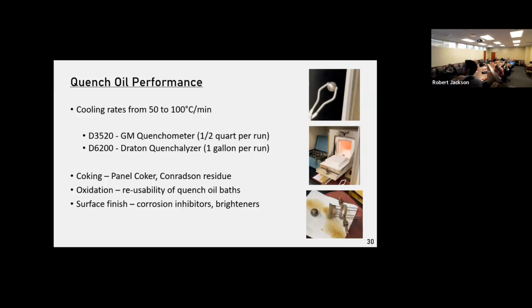Then you can go to quenchalizer. It takes more sample, it's a little more expensive, but this can actually get you instantaneous cooling rates at specific temperatures as well. So if you're a metallurgist, there's a lot more to talk about. But we also look at coking, oxidation, and surface finish. So when you retrieve this piece of metal, you don't want it to be covered in charcoal or burnt up or rusted. We want to make sure that we preserve this metal, even though it's gone through about 1,000 degrees of temperature change.